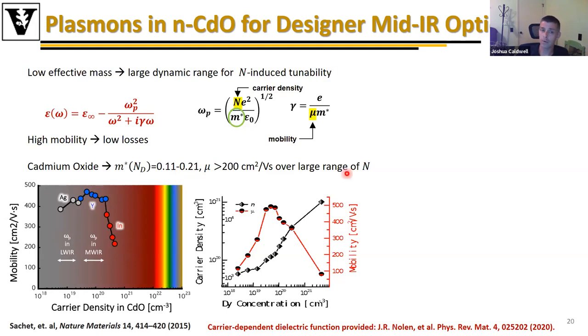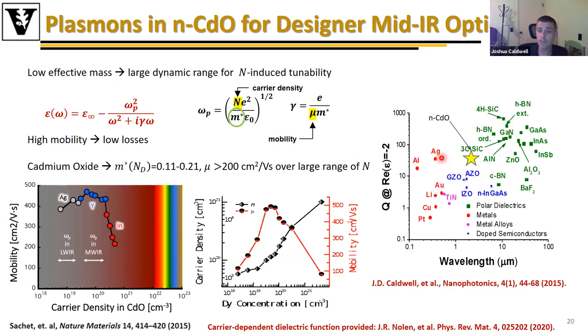Furthermore, as has been seen in a number of transition metal oxides, as I increase the carrier density, a healing of oxygen vacancies actually occurs, which causes the mobility to increase as opposed to traditionally decreasing as I increase the carrier density. So you see this increase in mobility with increasing carrier density, even at levels approaching 10 to the 20 free carrier concentrations. Which means this is a nominally low loss material across that entire spectral bandwidth. And if I therefore compare this, you can see a number of these phonon polariton materials here, of course, but n-type cadmium oxide in the mid-infrared is approaching that of silver in the visible for losses.